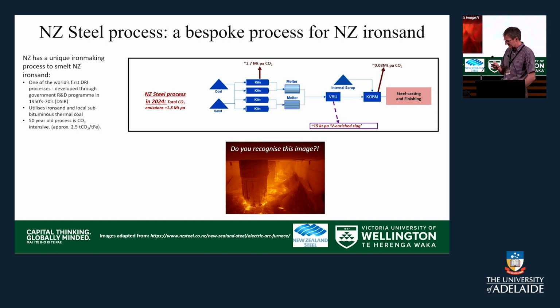However, the caveat to that is that we are running coal-fired kilns, and that means that the current process is actually pretty CO2 intensive. It's about 2.5 tons of CO2 per ton of steel. What we've got is coal and sand coming at the front. We've got kilns. We've got these two melters.